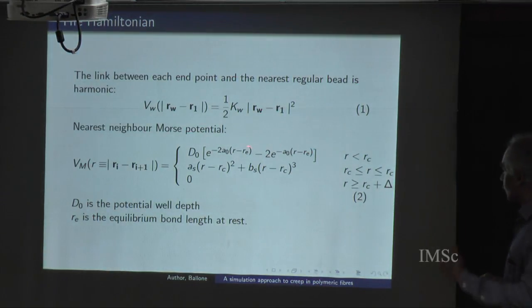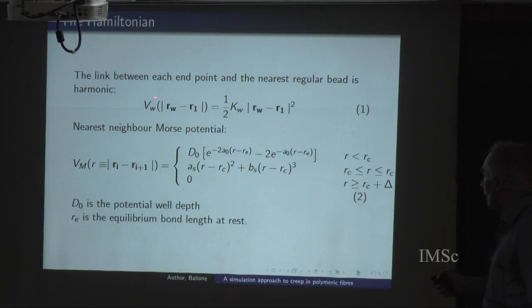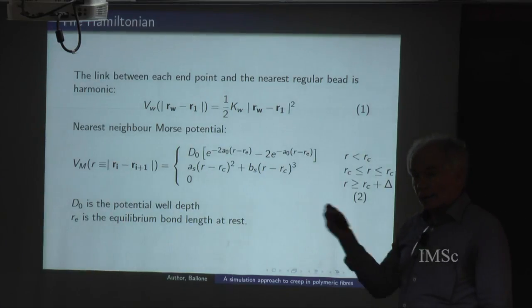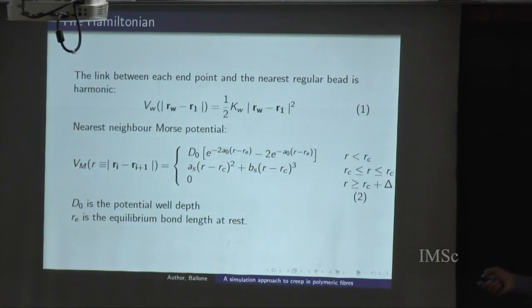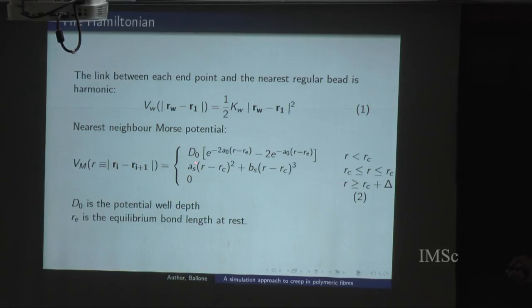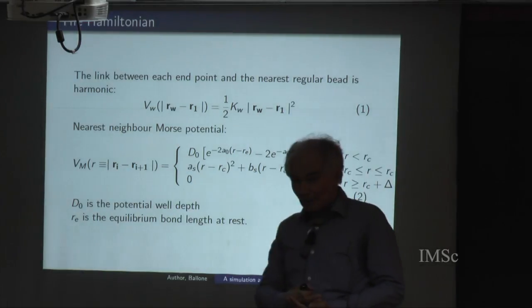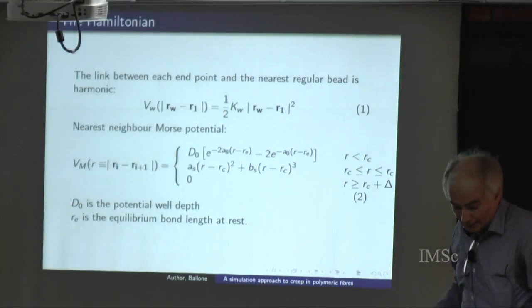Okay, so I do not want to go into the details because we have 10 minutes left, but essentially we have the interaction with the particle on the wall with the first bead that is, as I told, harmonic, and all the chains are defined by the Morse potential, that is something with a finite depth, but we cut it at a given distance. So the important parameters are the well depth, that is D0, and the equilibrium bond length. So we use scaled coordinates. Our unit of energy is k-Boltzmann T, and in our simulations, D0 is of the order of 10. So it's something that is strong, but not so strong that the bond cannot break by fluctuation.